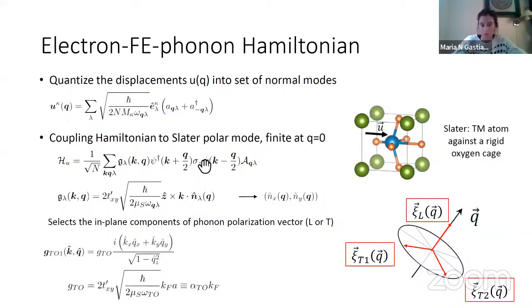Then the new part here is, first of all, that the vertex has this sigma, so it's a little bit more like a spin, a magnetic kind of coupling. And then it has this K, so it breaks inversion, and that's because the mode that I'm coupling to is also EU or A2U. It also breaks inversion, and then I can go ahead and write a basis where I couple only to the transverse component of the phonons. I get an analytical expression, and once I have it, I can use it for calculating transport or superconductivity or whatever process you're interested in.